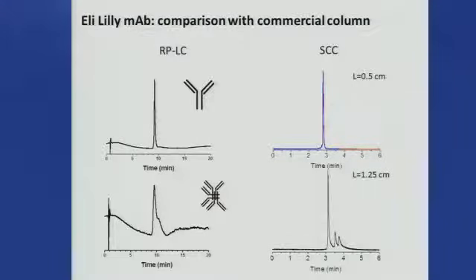This is a really neat result that we got. Compared with a reverse phase column, 1.7 micron particles. This is an Eli Lilly monoclonal antibody. Pure, so this is a sharp peak for the commercial column, sharp peak for ours. These are 3 replicates, that's why you see the different colors. So extremely reproducible. This is a 5 centimeter length, and ours is half of a centimeter.